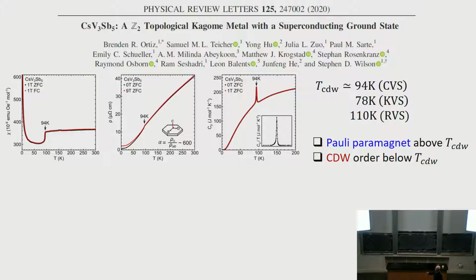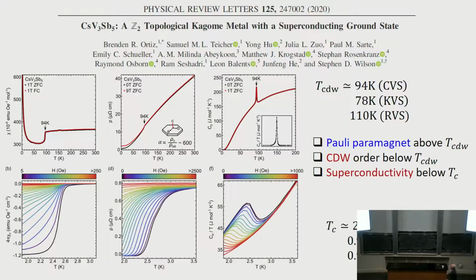And above the CDW transition is paramagnetic. So there are no local moment or not even very strong spin fluctuations, right? And then they go through a CDW transition. This is the heat capacity. This is the resistivity. There's about 600 anisotropy ratio of resistivities in plane and out of plane. And at low temperatures, they all become superconductors.